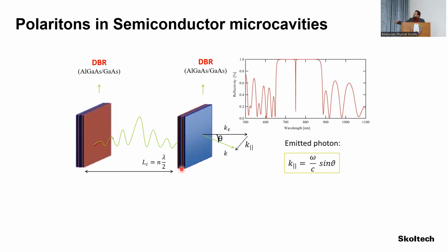We have a cavity which is usually a λ/2 cavity or a 3λ/2 cavity. It is a small cavity so that we have small volume, and therefore we can increase the Rabi splitting in the structure. But before I go there, let me show you the reflectivity as a function of wavelength. By using this kind of distributed Bragg reflectors, I create a stop band where I have practically reflectivity of almost 100%. And here you can see the cavity mode, the bare cavity mode.